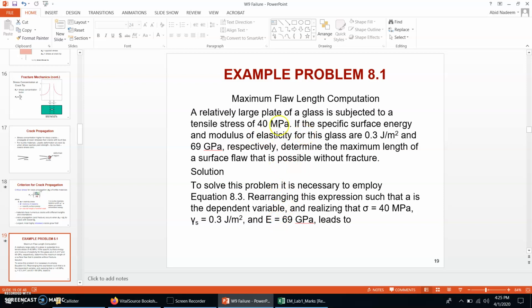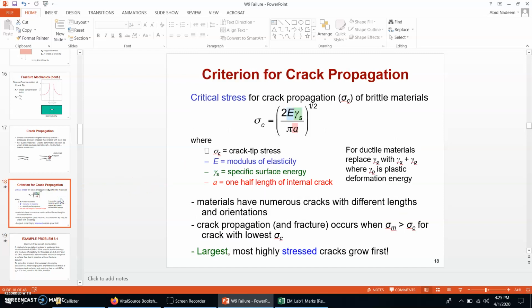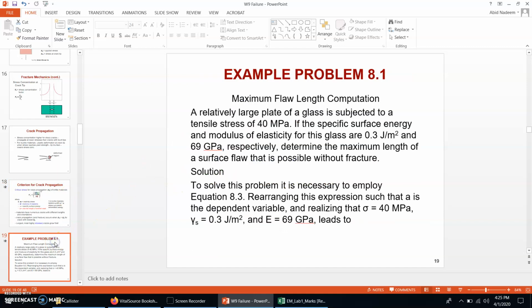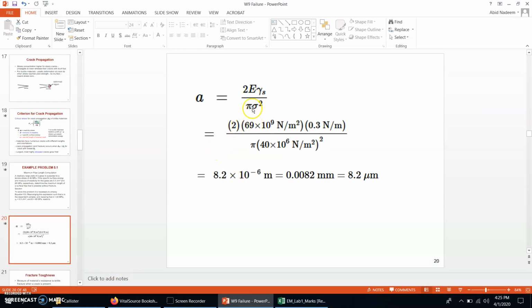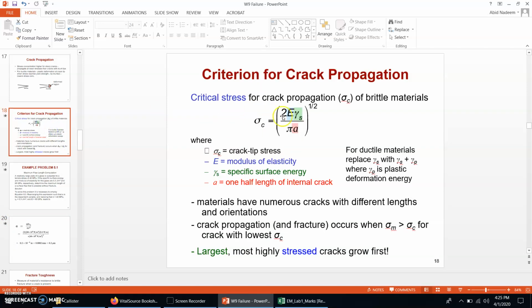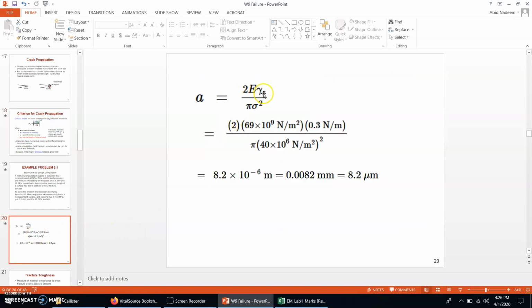So it is a simple, straightforward question. 69 gigapascal is the value of E, 0.3 joule per square meter is the value of gamma s, and 40 megapascal is the value of the stress, which will be used over here. So we can input these values in this equation, and then this is the solution. You can rearrange this equation to make it a equals 2E gamma s over pi sigma squared. Just input these values, and you get a value equal to 8.2 micrometer, or you can convert it into millimeters as well. So this will be the answer.